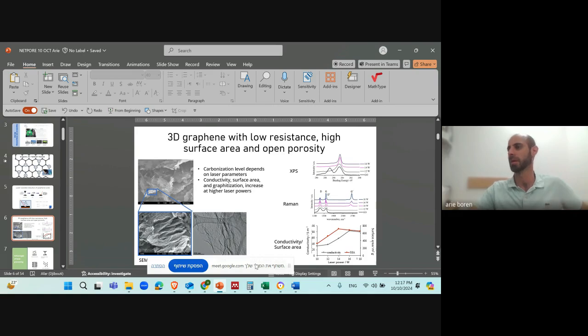And how do we know it is graphene? We just take it to spectroscopy. In XPS, you can see the black curve is for the GO. This is one of the precursors that we use. GO is, of course, graphene oxide. So it is an oxidized graphite, layers of graphene, oxygen, and then other graphene. But then you have to do two things: exfoliate it and reduce it, meaning eliminate the oxygen. And this is what the laser does.